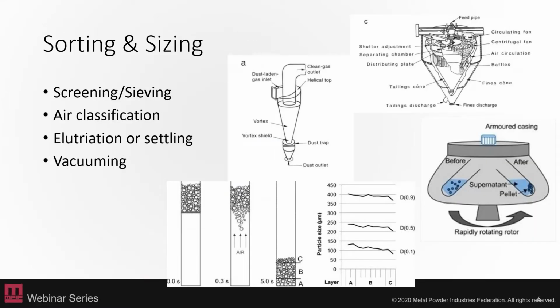When you're taking your powders and then sorting and sizing them to use only the powders that you want for your process, there are a number of different methods. You can use a standard screen or a sieve to process the powder as it goes through a grid of metal, or there are plastic grids too, to cut the size fraction at only the sizes that you want. And then there's also air classification methods, which is more traditionally used, shown there in A and C, where your powders are injected into a cylindrical vortex where the powders can come out at different sizes based upon how you set your gas parameters and how your chamber is configured.